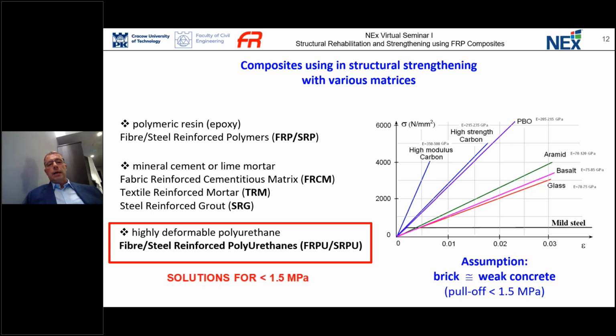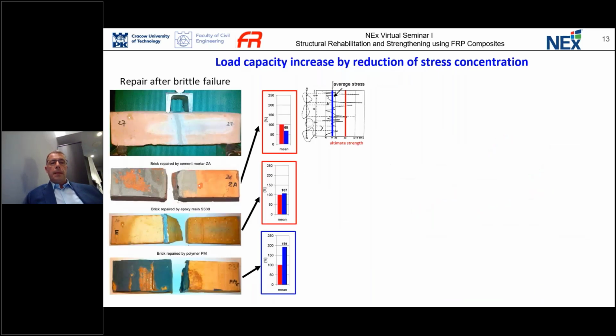Let me make an assumption for the next comparison presentation that brick and weak concrete are practically of the same strength. So in the pull-off test, we have under 1.5 megapascal. So I would like to present some tests. This is the brick tested in 4-point bending. So the original brick was broken. Next, in the place of the crack, the brick was strengthened, rebonded again with 3 kinds of materials.